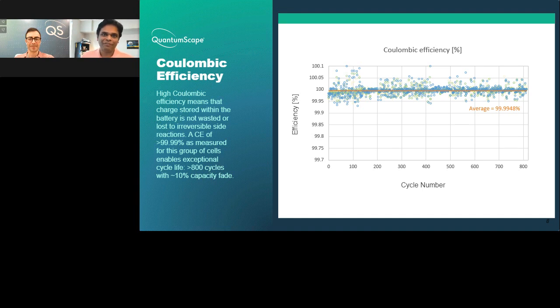Yeah, so coulombic efficiency is one of the key metrics, and in the context of lithium metal, it's particularly important. Typically, in cells that involve liquid electrolytes in lithium metal, their coulombic efficiency is much lower than this number. And when you have a number that's maybe 99.9, that means that in a few tens of cycles, if you had no excess lithium, your capacity would degrade to about 80%. So in order to accommodate this, what is typically done in the liquid electrolyte world is they use an expensive lithium foil. So that's the way that they get around this problem.